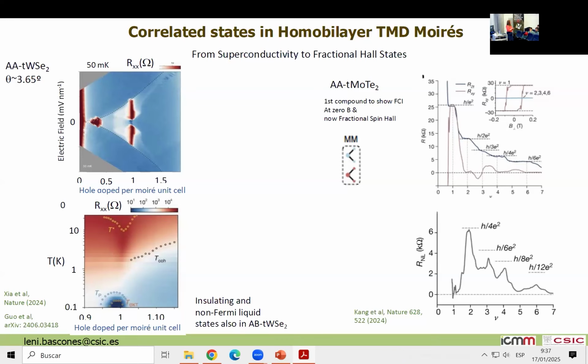People didn't find superconductivity in this twist structure in other systems except graphene bilayers, graphene moirés. Very recently, it has been confirmed in this compound that superconductivity can also appear, okay? And you can see here also how this superconducting region, which is what you see here, again with a perpendicular electric field, is in between two very insulating states, which are also correlated states.